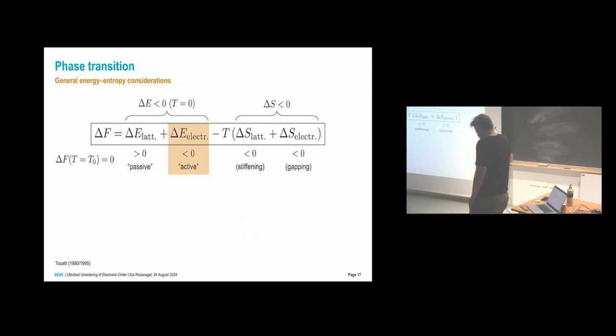Okay, then what about this transition? So this is now the energy entropy argument. So this is the free energy. You have here energy, it should be below zero at T equals zero, and you have an entropy change between the two states, and this is also typically below zero. It's negative because phonons get stiffer, and the electronic structure gets gapped, and this leads to lower entropy. Yeah, and so this is negative. And if you go through zero with this free energy change at some temperature, then this indicates a transition. So these are the active terms.